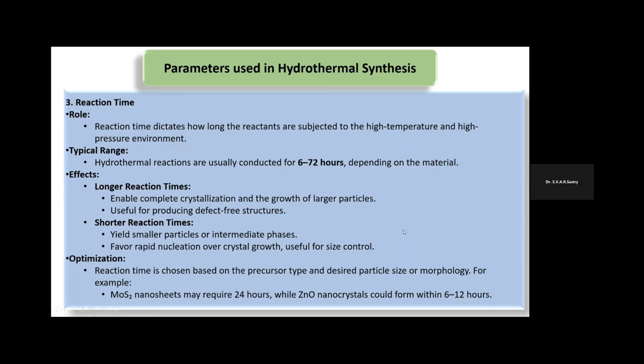The third parameter is reaction time. It dictates how long the reactants are subjected to the high temperature and high pressure environment. The typical range is between 6 to 72 hours, depending on the material of which we want to synthesize nanoparticles. Long reaction time enables complete crystallization and the growth of larger nanoparticles, useful for production of defect-free structures in the nanomaterials.